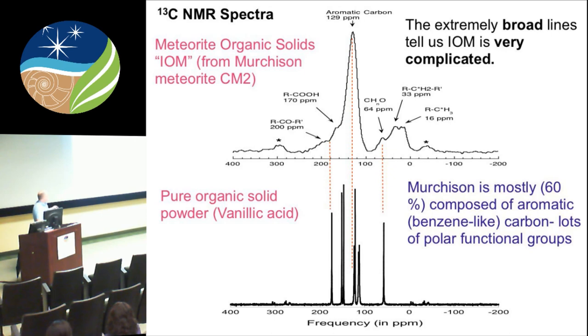And what I'm showing you here is that the broad lines that you see are not an issue of resolution limits for our NMR. Rather, what it's looking at is chemical complexity. By and large, you see most of the carbon is in this peak, and this is aromatic carbon, like a benzene ring or something related to that. But you see various shoulders that correspond to different bonding environments the carbon finds itself in. So the bottom line is Murchison is mostly aromatic carbon, and it has lots of what we call polar functional groups, carbon bonded to oxygen.